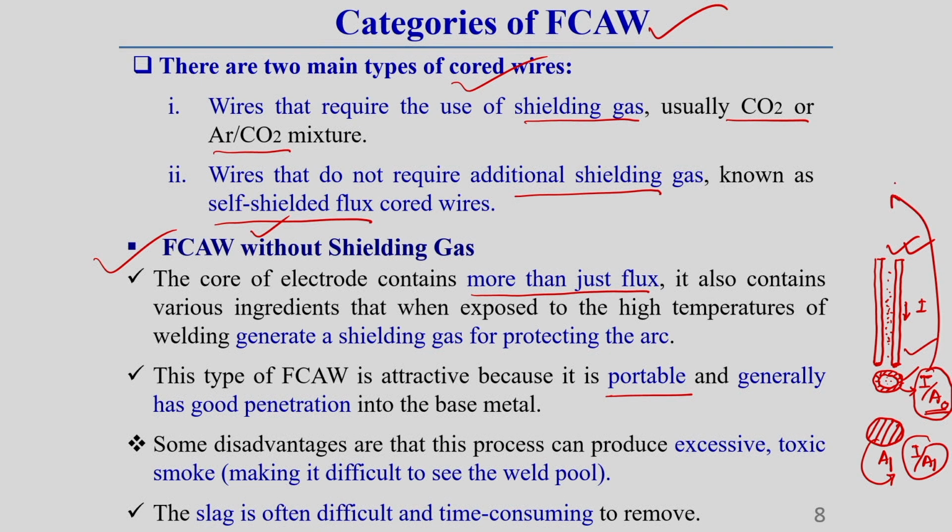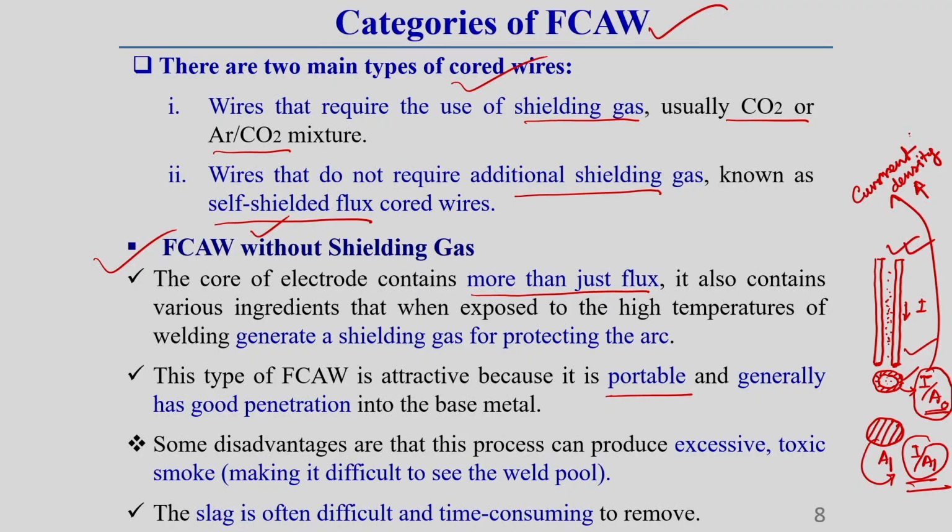This is called current density. So flux core wire has a higher current density than solid wire, because the area carrying current is smaller, since generally the flux does not carry the current. Now, as this current density is more, it creates a more forceful arc.